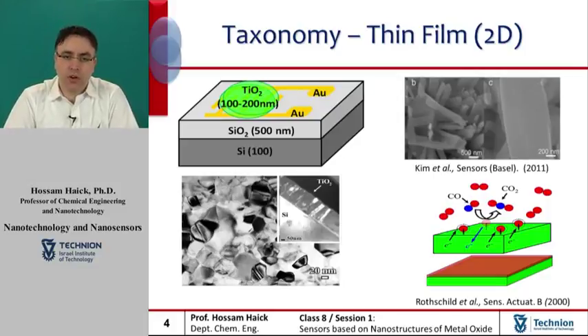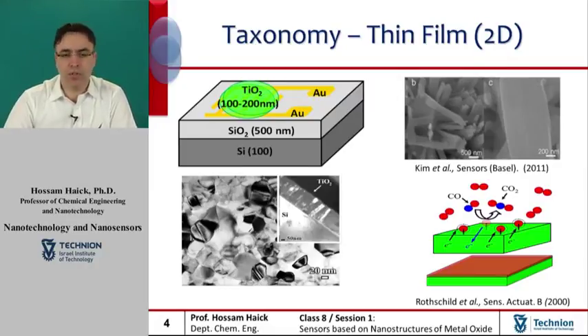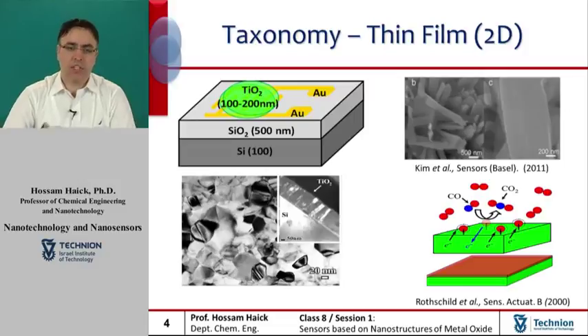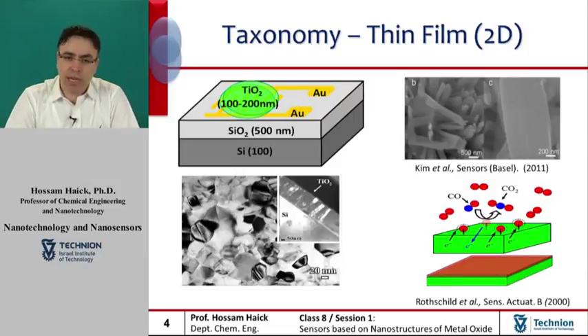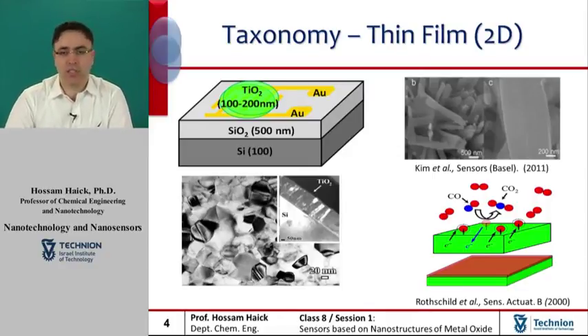Commercial sensors are commonly based on thin layers of metal oxide semiconductors. Although this design has become a success story from the commercial point of view, it presents two major drawbacks. The first drawback is related to the high power consumption, which hinders the use of metal oxide films in portable and autonomous systems. The second drawback is the poor stability of the metal oxide films, derived from multiple causes such as grain boundary contributions among the nanoparticles inside the sensing layer itself.